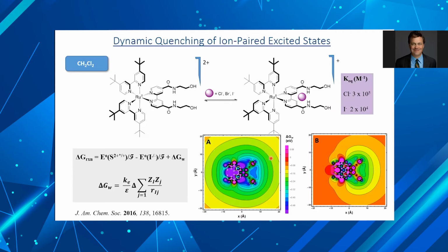But using theoretical approaches and density functional theory, Ludo went through and assigned partial charges to all the atoms in the molecule and worked out the so-called work terms in the Rehm-Weller expression. And what I can tell you for sure is that the theory predicts exactly where the halide binds. The first halide went here, and in some cases he could see the second halide go here when there was one sitting. And he could confirm that by NMR. But the stabilization he measured was very similar to the equilibrium constants, but not quite the same. And we feel we need a larger database to really test whether the theoretical predictions are in line with experiment.